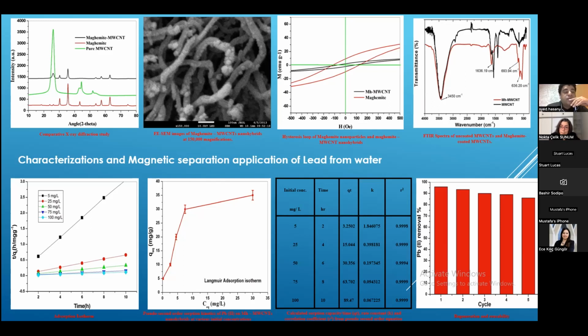It means that we have found a nanohybrid with small crystals of iron oxide. By microscopic techniques, we calculated the nanoparticle size to be around 20 nanometers, whereas the crystal size was much smaller, around 15 nanometers.